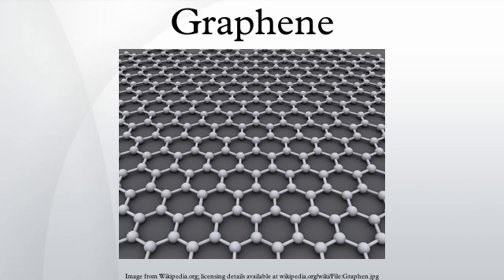Graphene sheets, held together by van der Waals forces, were suspended over SiO2 cavities where an AFM tip was probed to test its mechanical properties. Its spring constant was in the range 1 to 5 newtons per meter and the stiffness was 0.5 TPa, which differs from that of bulk graphite. These high values make graphene very strong and rigid. These intrinsic properties could lead to using graphene for NEMS applications such as pressure sensors and resonators.